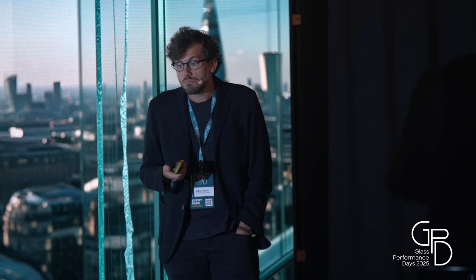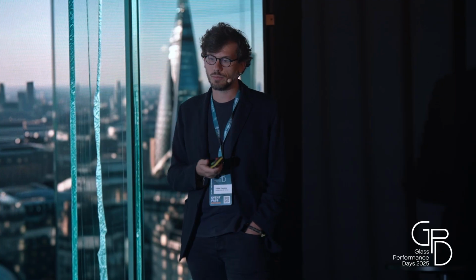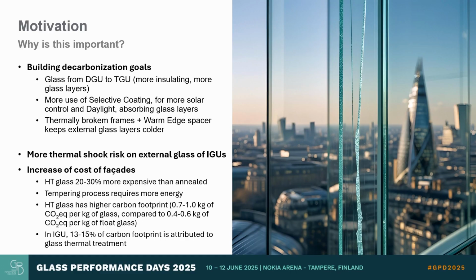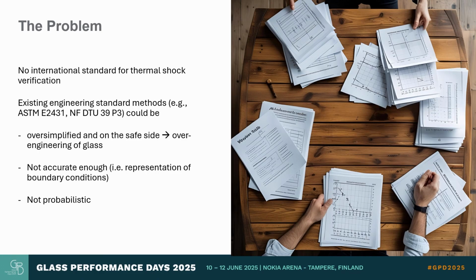The way this is usually avoided is to heat-treat the glass, in conditions in which you can use heat-treated glass, depending on the kind of coatings and curvatures that you have. Eventually, this ends up in increased costs of heat-treated glass compared to annealed. The tempering process requires more energy, and eventually this is a higher carbon footprint. So in an IGU, more or less 15% of the embodied carbon A1 to A3 can be attributed to glass thermal treatment. So there's also an environmental value there.